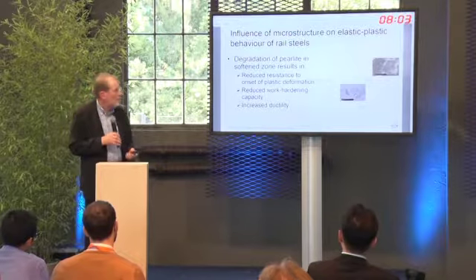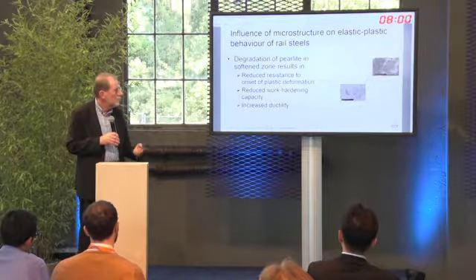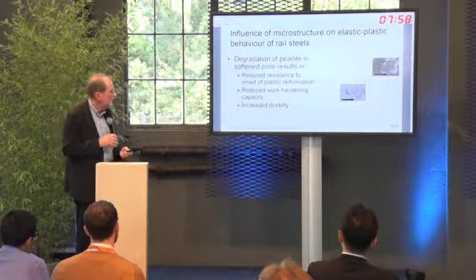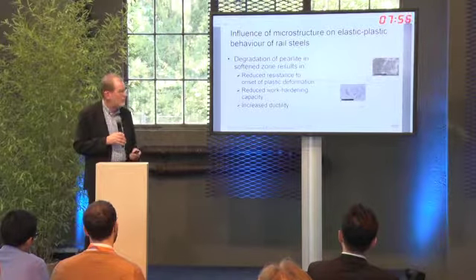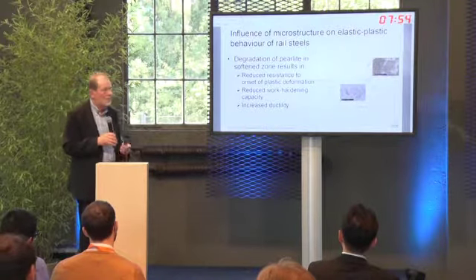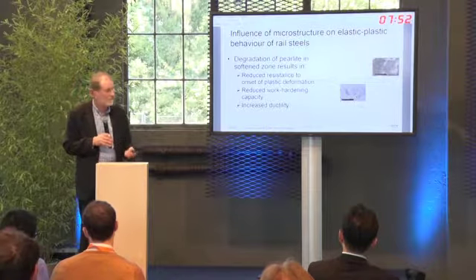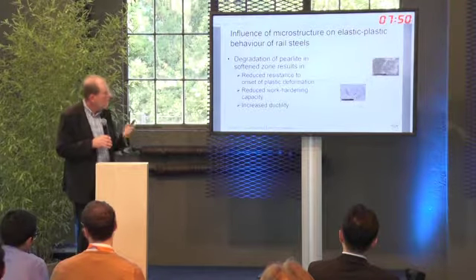Yield strength's much lower, the ductility is much higher, perhaps less evidence of work hardening. So the material in the softened zone is just not going to behave the same way if you're trying to predict ratcheting behaviour.